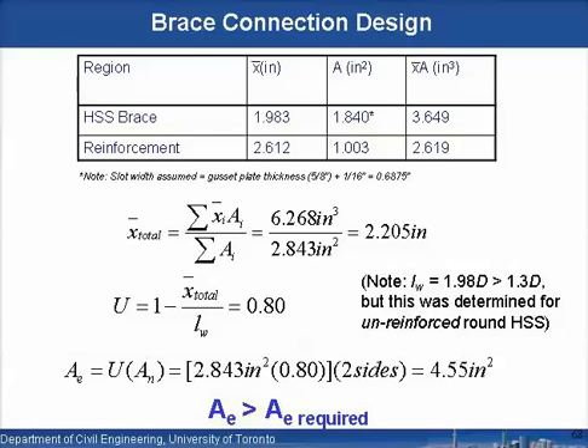Now, if you looked in the specification, the AISC spec, you would note for unreinforced connections a little note that for slotted plates into round HSS, if the length of the weld exceeds 1.3 D, then the connection is 100% effective and has no shear lag reduction. And we're up to actually 1.98 D in our insertion length, much beyond that. So the chances are we have no shear lag reduction here as well. But this little rule was determined for unreinforced round HSS, and we've now got a reinforced HSS connection, so it's a different animal really.